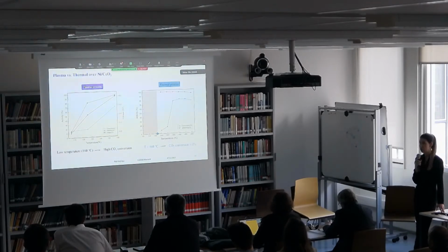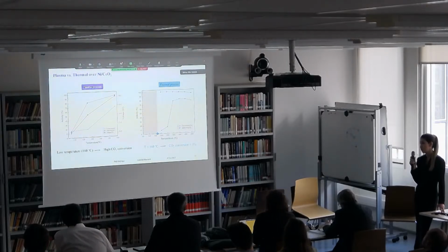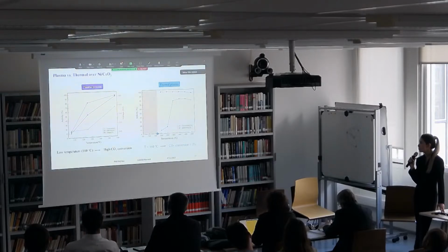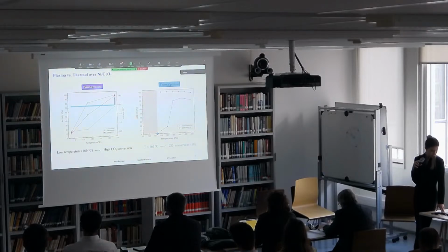In the first study, as I mentioned, the nickel ceria catalyst will be performed in plasma and thermal. But just to give you a simple comparison between plasma process and thermal, as can be seen, in the plasma process, the CO2 conversion reached 72% at 160 degrees. I should mention that this temperature is the reactor temperature. While in the thermal process, there is no conversion below 160 degrees, basically until 300 degrees. Then by increasing the temperature, conversion reached 78%.